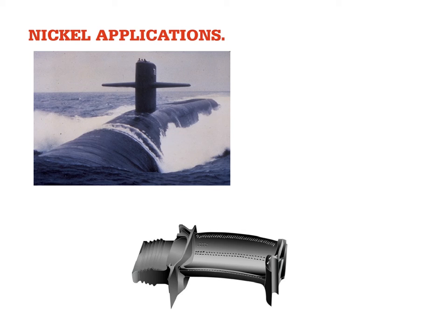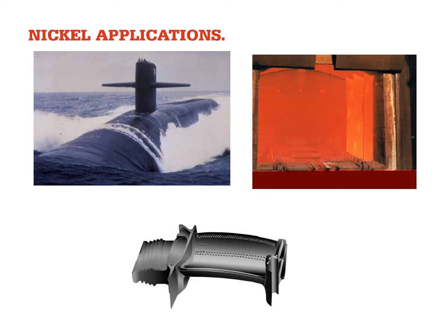And here the precipitation strengthening of the nickel alloys increases their creep resistance at very high temperatures, which is the limiting factor for these high pressure turbine blades. We need to have creep resistance at the highest possible temperature. The hotter you can run your engine, the greater the fuel efficiency. And then finally, this orange picture is the application of nickel as the containment in a high temperature furnace.